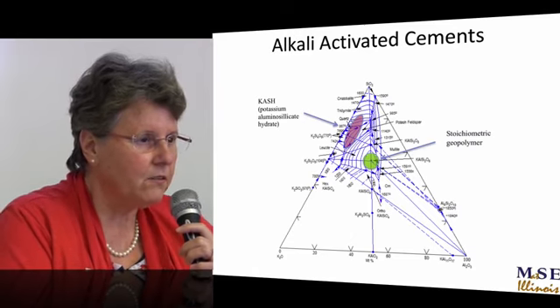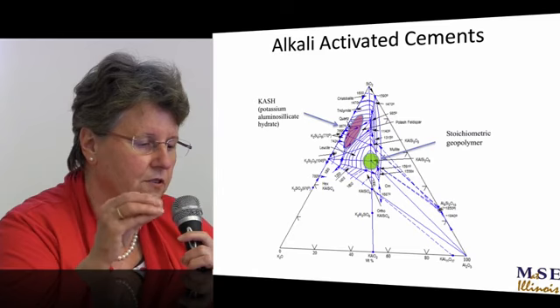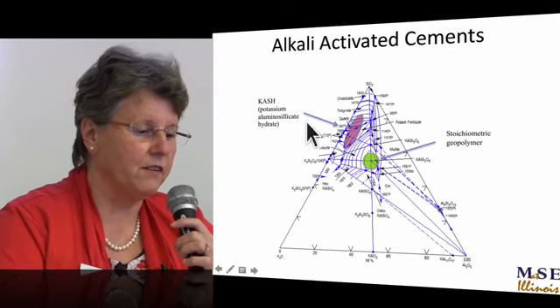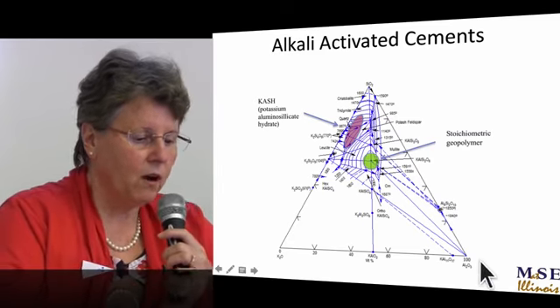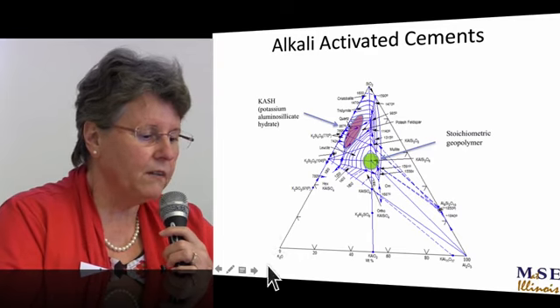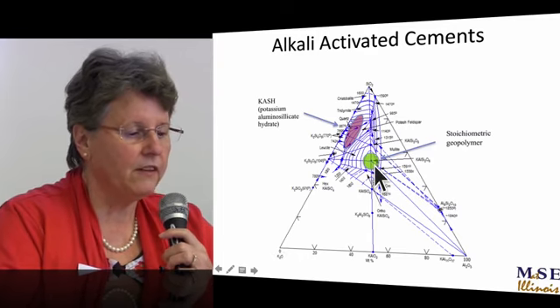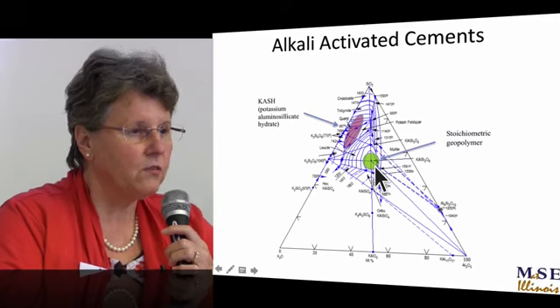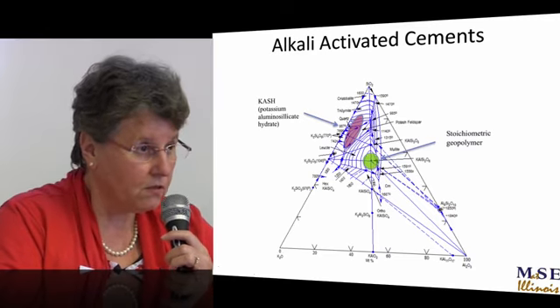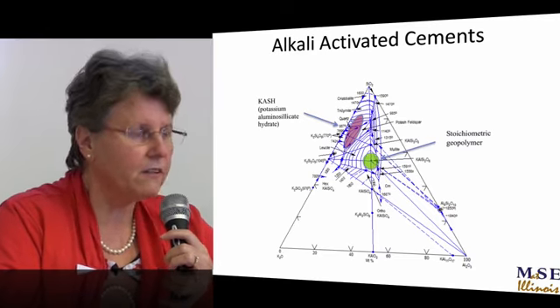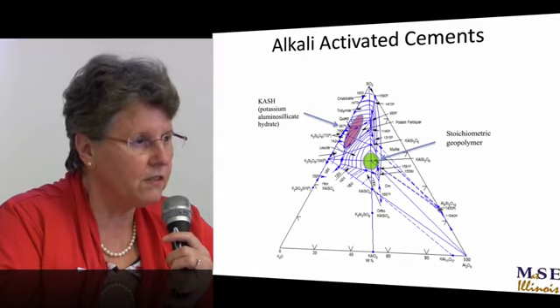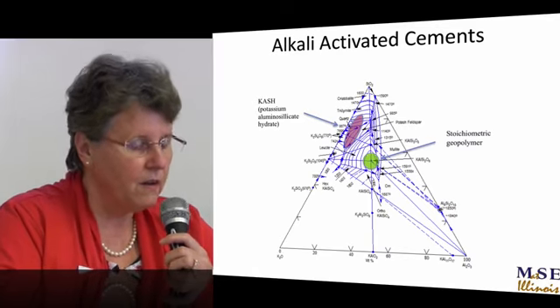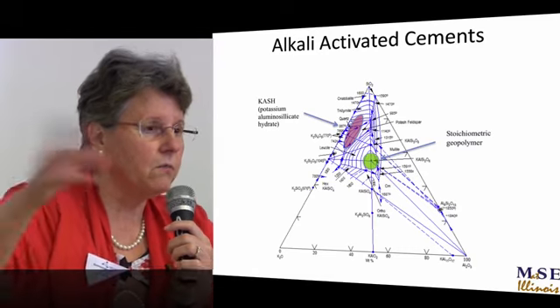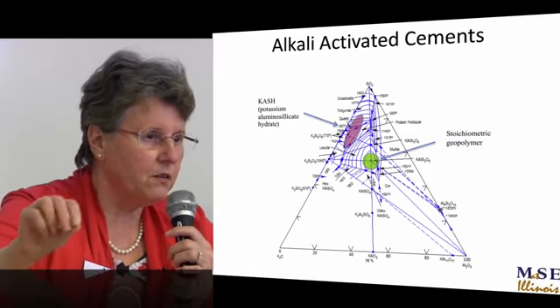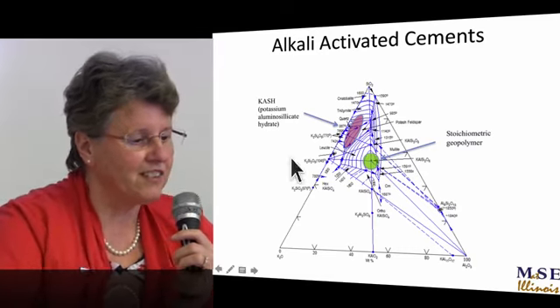And I always found that the characteristic microstructure had a characteristic chemistry: 1 alumina, 1 group 1 oxide, and 4 silica. And that's this. So that's what I call a geopolymer. It's a stoichiometric geopolymer, and that's because that's what I see in the TEM all the time. Not the overall mixture I started with, but geopolymer's got a characteristic microstructure.